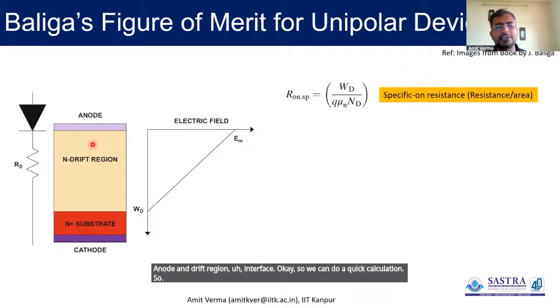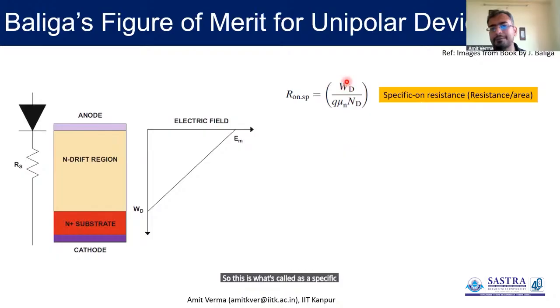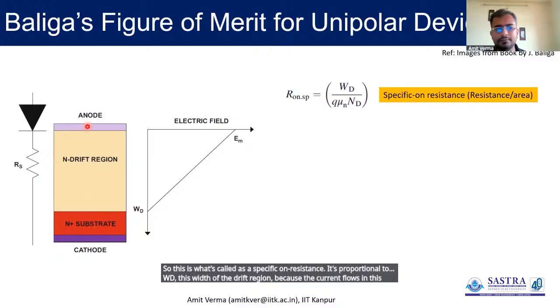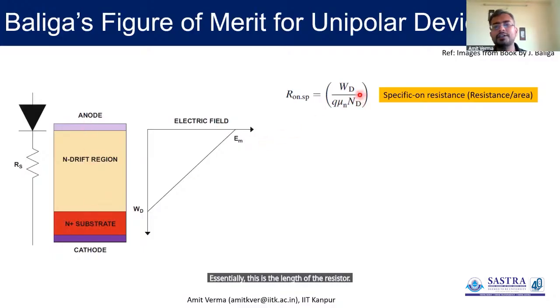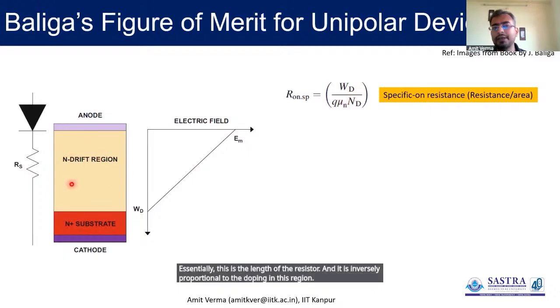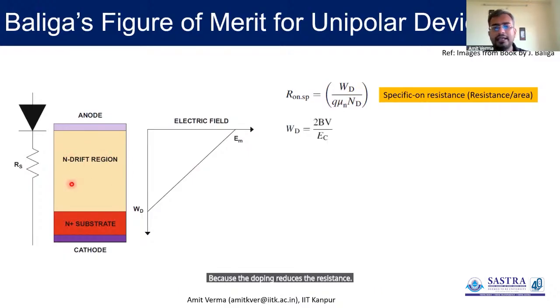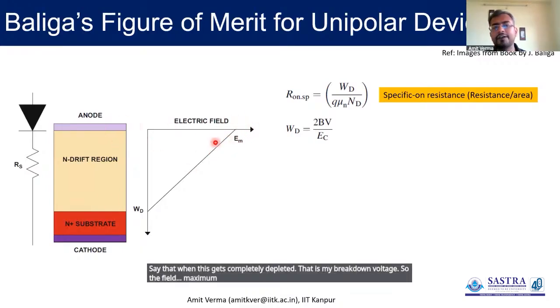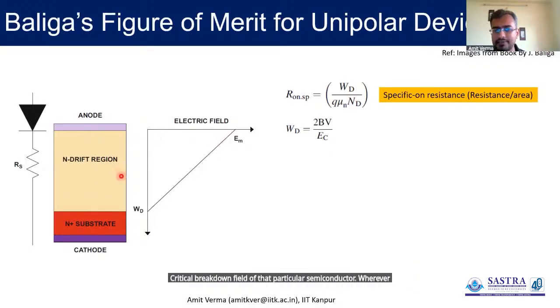So in the on-state, essentially there is no depletion. So this is what contributes to on-state resistance. This is what's called the specific on-resistance. It's proportional to WD, the width of the drift region, because the current flows in this direction. So essentially this is the length of the resistor, and it is inversely proportional to the doping in this region because the doping reduces the resistance. Then when this gets completely depleted, that is my breakdown voltage. So the maximum field at this interface is the critical breakdown field of that particular semiconductor wherever we have made this device. So the area under this curve, essentially half of WD times EC, is the breakdown voltage. This is this equation. Okay.